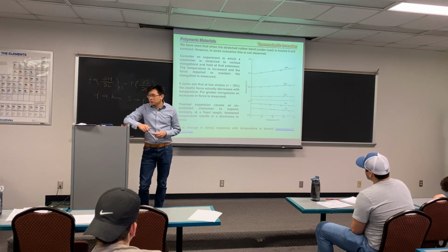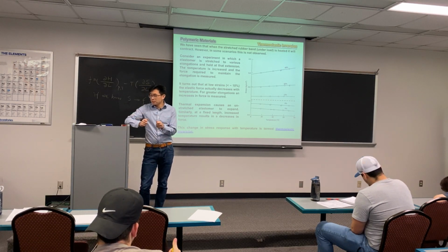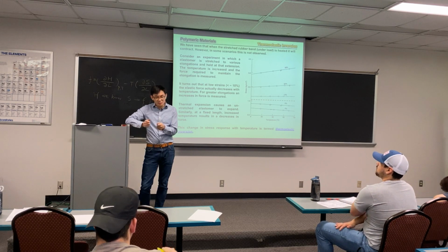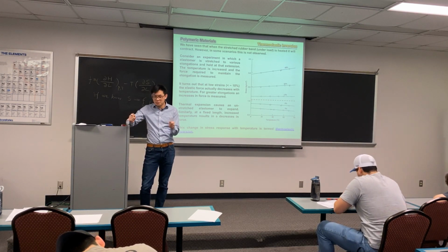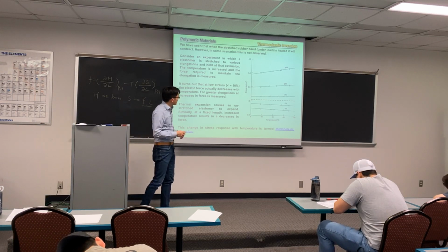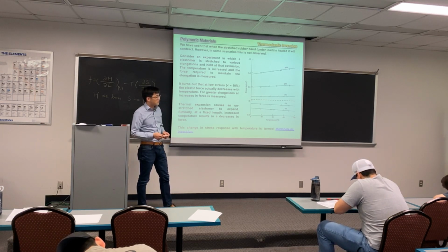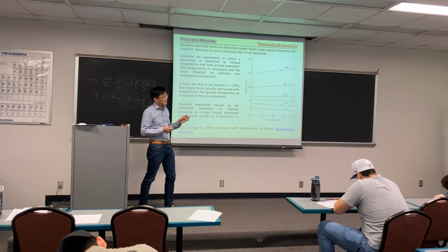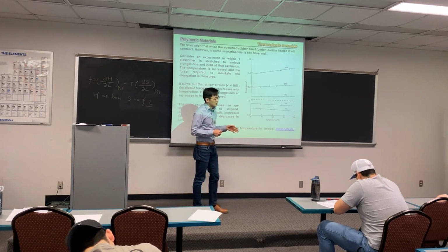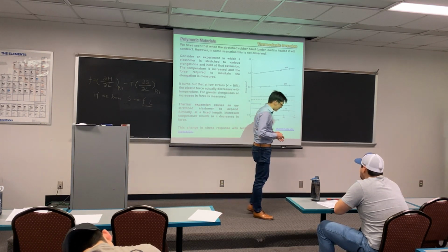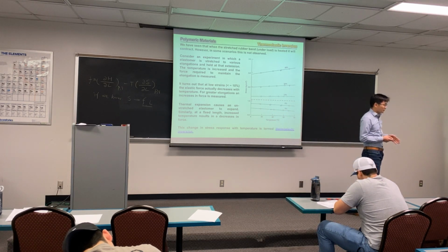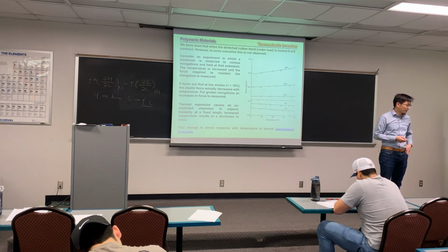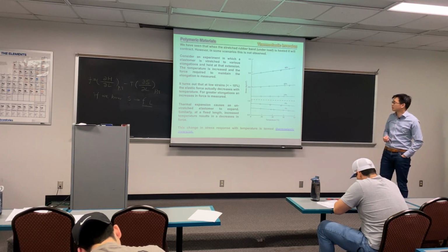This is a general truth for a large degree of strain. If you pull the rubber band from a little bit to a lot, it's very obvious. But there is one concept I want to introduce: at a small deformation, thermal expansion will dominate, and you wouldn't actually see that phenomenon.